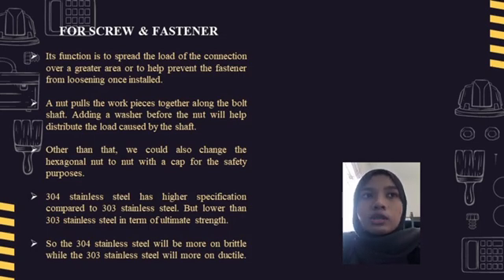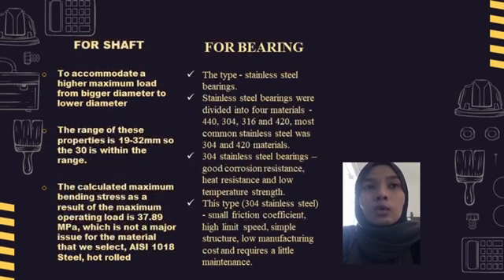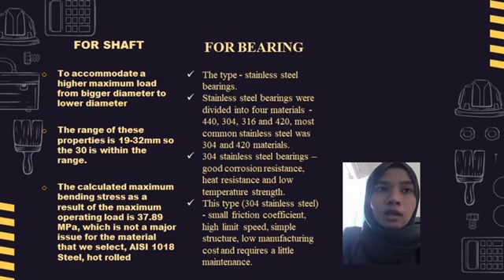Based on the comparison of screw and fastener properties in the table of two types of material, the 304 stainless steel has a higher specification compared to 303 stainless steel. However, the ultimate strength of 304 stainless steel is lower than 303 stainless steel. So the 304 stainless steel will be more brittle, while 303 stainless steel will be more ductile. From the result, we can know that in brittle material, the ultimate tensile strength is close to the yield point, whereas in ductile materials, the ultimate tensile strength can be higher. For the shaft, we modify the shaft diameter from high to low to accommodate the higher maximum load. The range of this property is within the range that we wanted. The calculated maximum bending stress of the maximum operating load is 37.89 MPa, which is not a major issue for the material that we select.